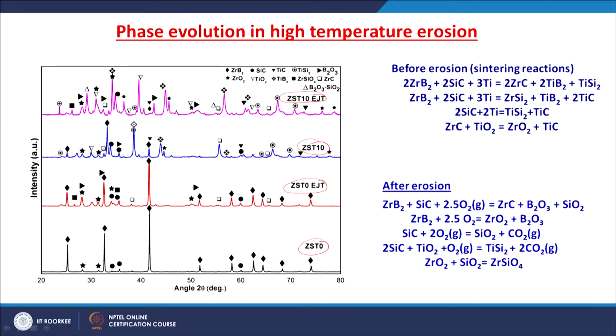Now, you see the phases before erosion are just zirconium diboride, silicon carbide and zirconium oxide for the sample without titanium. When titanium was added in the powder mixture and sintering was done, we have certain sintering reactions before erosion: zirconium diboride with silicon carbide with titanium gives zirconium carbide, titanium diboride, and also zirconium silicide, titanium boride, titanium carbide, titanium silicide, zirconium oxide. So, several possible reactions can be thought. After erosion we still have a few new phases formed on the surface.